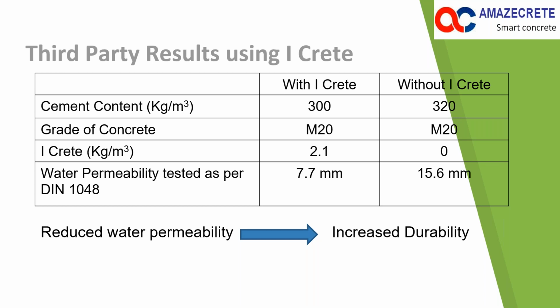And I want to bring another important point here: when we are using 320 kgs to 300 kgs, there is always a slight increase in the water cement ratio in the iCrete incorporated, cement reduced mixes. So even in a mix with a higher water cement ratio and lesser cementitious content, this product gives equal or better strength and better permeability. This is the beauty of this product.